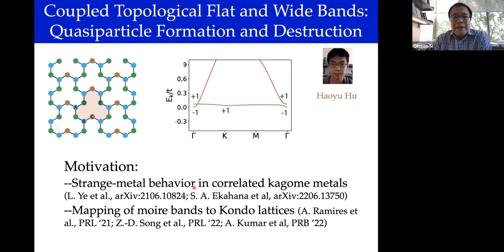And the motivation came from two experiments. One is from Joe Checkelsky's group in nickel three indium. I hope I got the formula right. That showed evidence for flat band and wide bands and T-linear resistivity. This is the work from PSI, Gabriel Aeppli, on one of the iron-tin family members that have, from ARPES, some indication of a strange metal. So this made an impression on me, and we thought we would think about such systems.